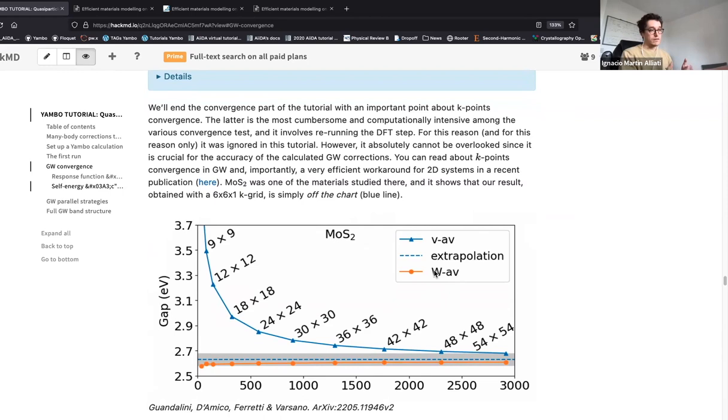It comes back to this idea that the screening is sharply peaked at gamma. As you increase the sampling of the grid, you are including points closer and closer to gamma, and you're capturing part of this dependence. But you can do so as well if you use a coarser grid and then treat gamma specially, fitting a polynomial to this sharply peaked function at gamma, and then you get a really impressive speed up in the calculation.